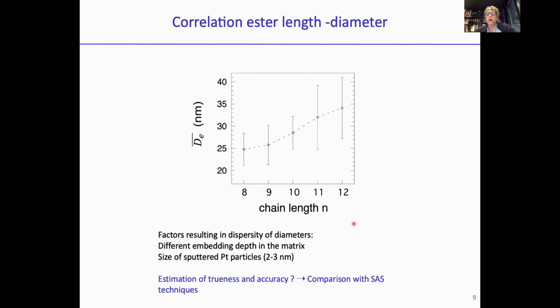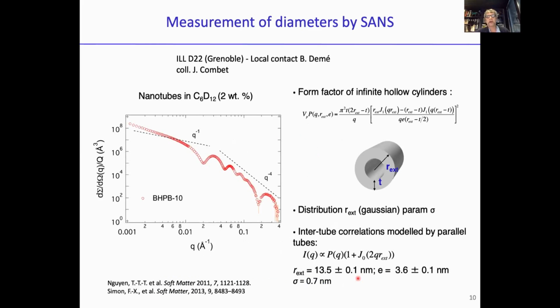And what we were interested in was to know what do we measure. We wanted to estimate the trueness and the accuracy of what we measure. And the question arises because when we do a freeze fracture, we have a replica, so it's prone to artifacts. Especially we sputtered platinum particles, and they have a given size. And also the objects are more or less deeply embedded in the matrix. So we made a systematic error in measuring this diameter. So that's why we compare it with small angle neutron and X-ray scattering techniques.